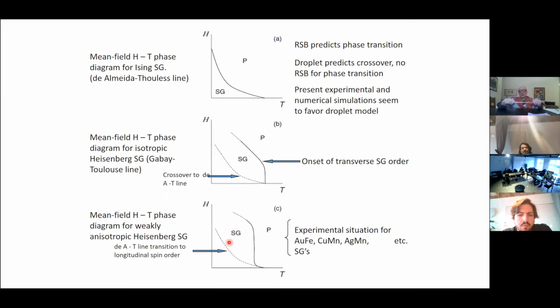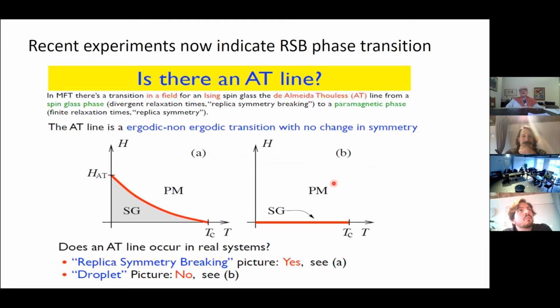And let me then finally ask the question, since I'm running out of time. The mean field theory predicts the famous de Almeida-Thouless line, that there is a phase transition from ergodic paramagnet to non-ergodic spin glass. And so if we jump on to the next slide, is there an AT line? This is what we experiments are looking at. The two theories are radically different here. There is the phase transition model of Parisi, and there is then the crossover, a smearing out. There's no spin glass phase in a magnetic field, even a tiny field. If I look at the experiments today, I see that there is more recent experiment and simulation data, simulation conclusions, that it's this type, it's this A instead of the B. So this is an added indication for the validity of replica symmetry breaking.